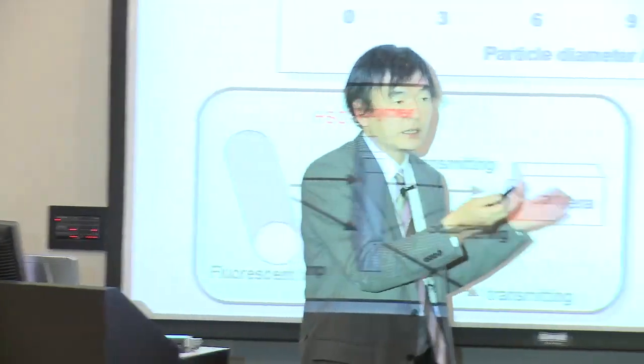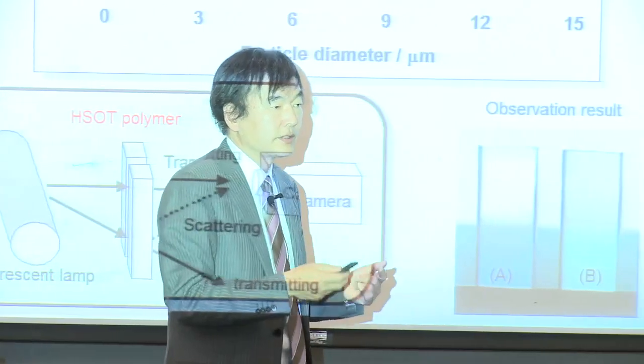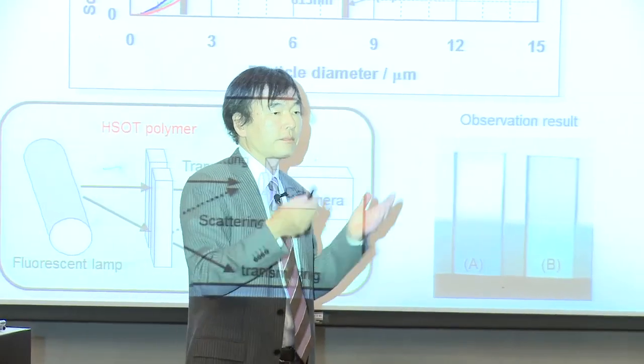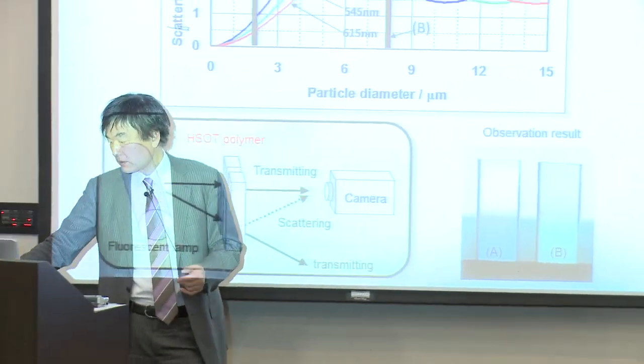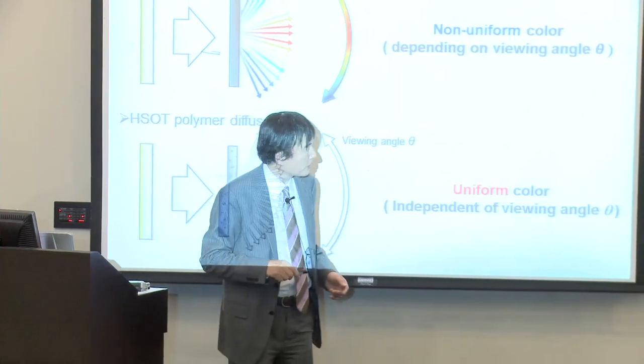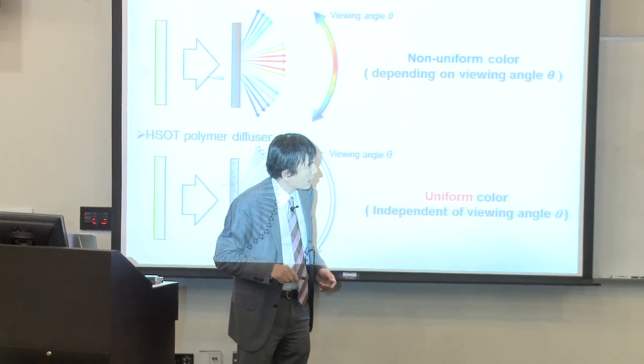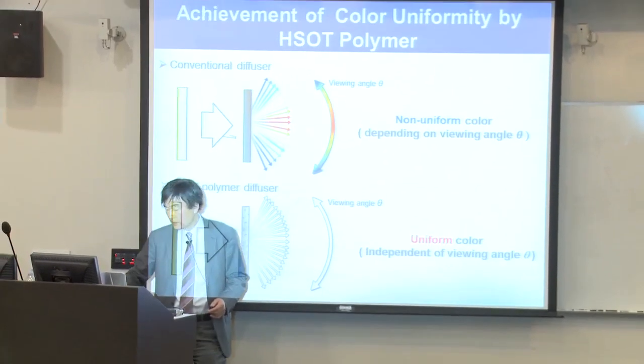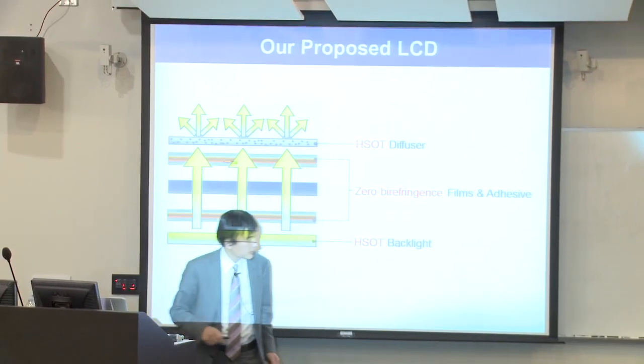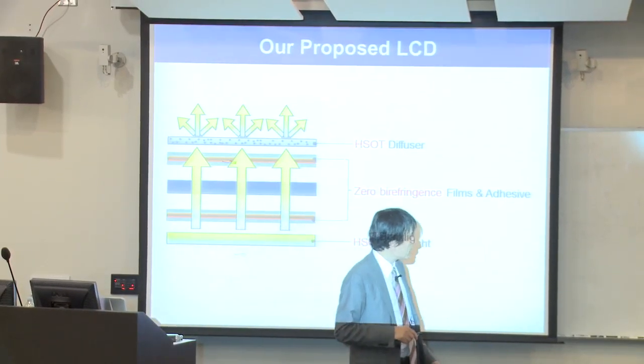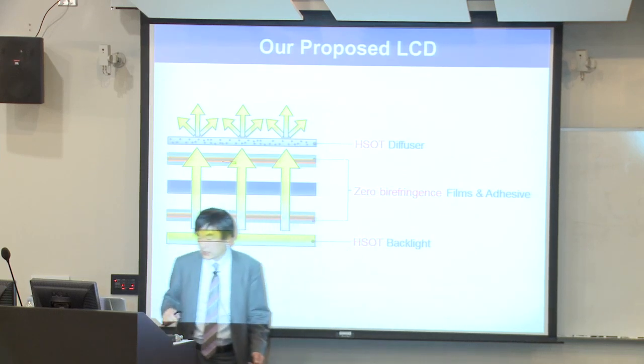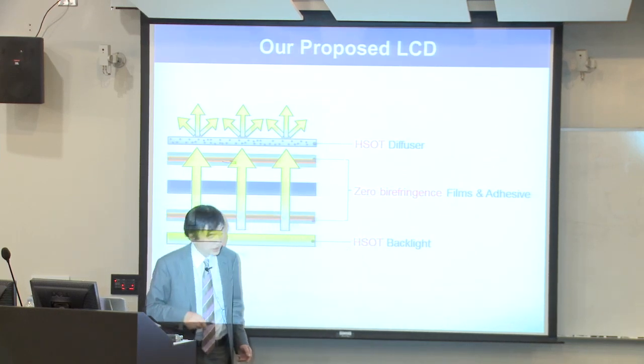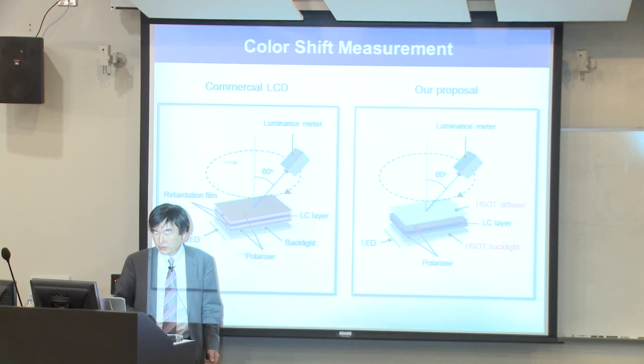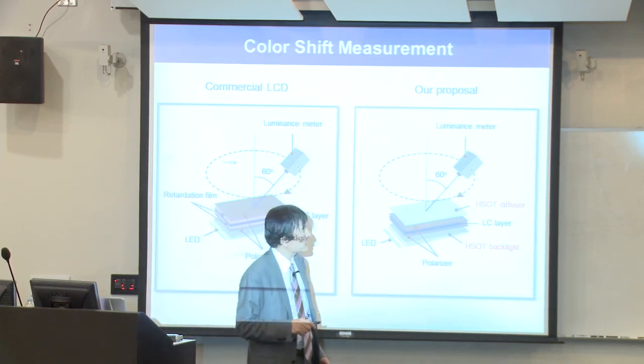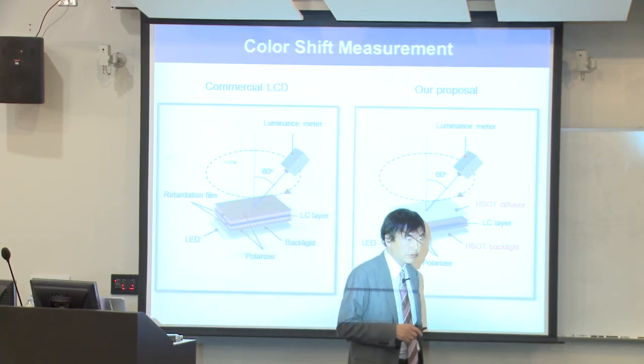Then we find this result as a patent. And the patent was issued. Now we obtain completely uniform view. Now, this is our proposed LCD without using retardation films. And we measure the color shift. That is the most important characteristic.